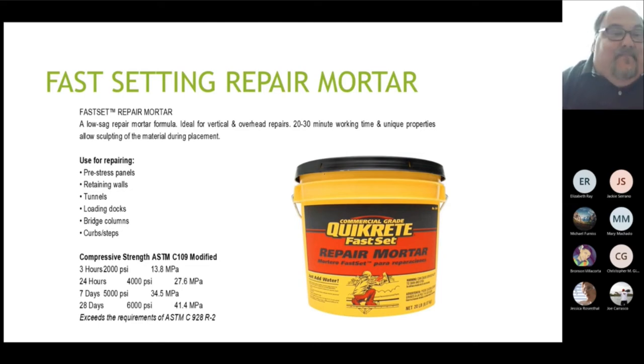You're looking at like 6,000 psi, but it's the bond strength and the actual strength of the material staying in place. This is one of those ones, if you have one material on your truck that's going to get you through a day, this is pretty much the one. I've gone feather edge with it, but it was underneath the carpeting, so I honestly can't tell you how it turned out.